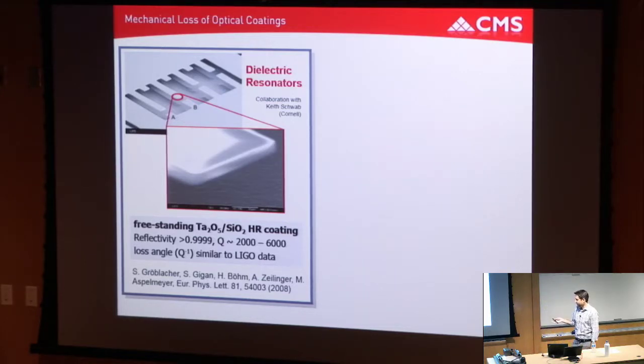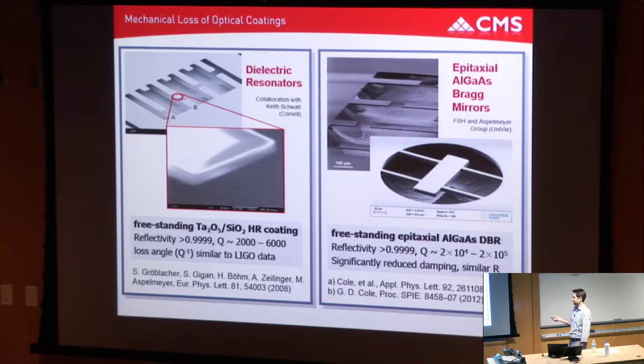For the cavity cooling experiments, we needed much higher Qs. We needed Qs on the 100,000 and up level. So we were a couple orders of magnitude away from where we needed to be. We have a lot more flexibility than, say, LIGO, so we can run through other options in terms of materials. My suggestion was to work with these single crystal semiconductors. I knew we could get comparable optical quality. And the intuition was just, well, it's a high quality single crystal semiconductor, and so the mechanical loss is lower. The quality factor will be higher.